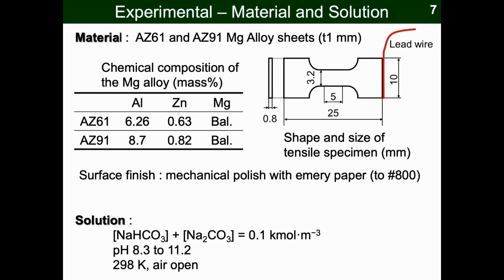Material was AZ61 and 91 alloy. And this is cut into this tensile specimen shape. And the surface was mechanically polished with a dry emery paper. Then applied to the EAC test. Solution is a carbonate buffer solution of pH from 8.3 to 11.2. The solution was used at almost room temperature and air open condition.